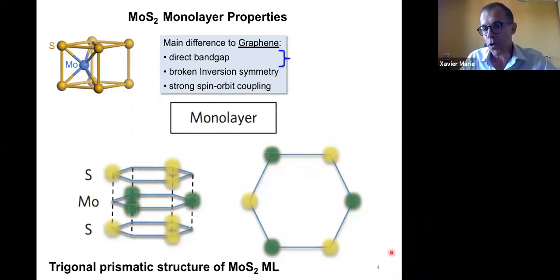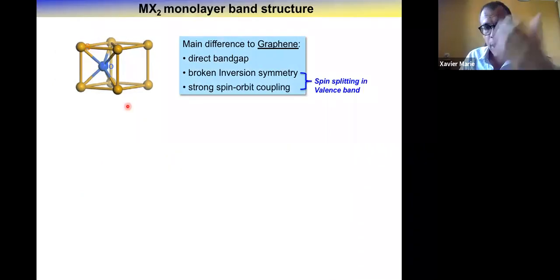If you look at the top view, you recover the hexagonal structure. And because of that, you have in the elementary lattice a broken inversion symmetry. And in addition, molybdenum, tungsten, the transition metal is rather heavy.